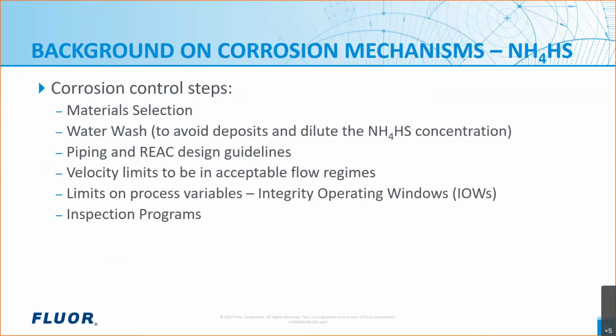So the first step, if you feel you're going to have a risk of corrosion, is the material selection. And then if you're staying with carbon steels, especially, but even with cases where you've upgraded the air cooler, because you might still have some carbon steel piping where you have the carbon steel separator, it's still very important to implement the other corrosion control steps.